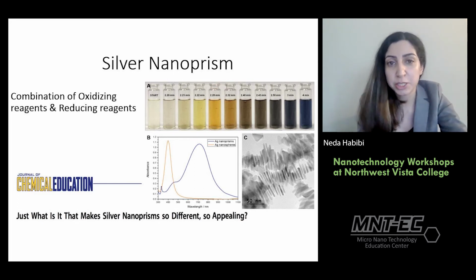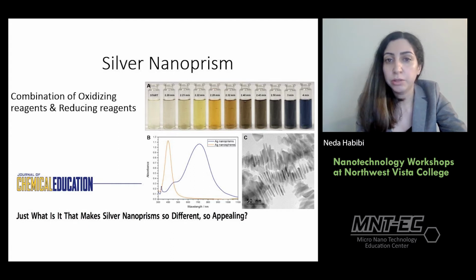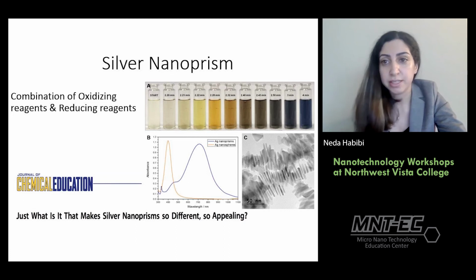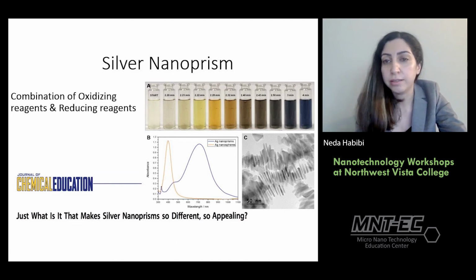In this experiment, once you start, at some point you add the sodium borohydride, and you have a very quick color change. Just in 3-4 minutes, the color changes from yellow to brown and then blue. And the blue color means that you actually have silver nanoprisms, because the silver nanoparticle is mostly black in color.